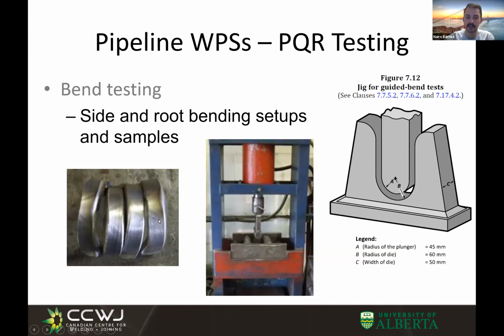But there's acceptance criteria. Very often within these tests, you'll see small micro cracks develop, especially in the heat affected zone or at the weld's root. Some of those cracks could be acceptable. The acceptance criteria is all listed within the code, but some of them are going to be unacceptable. Or if you bend it and porosity starts to show up that you didn't see when the sample was just cut, all those things are what they're looking for to give it a pass-fail criteria.